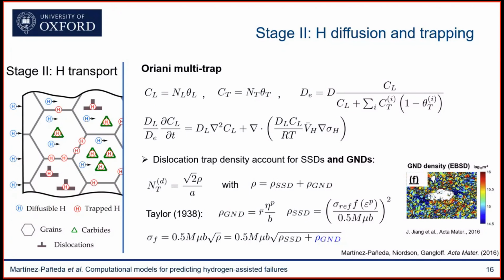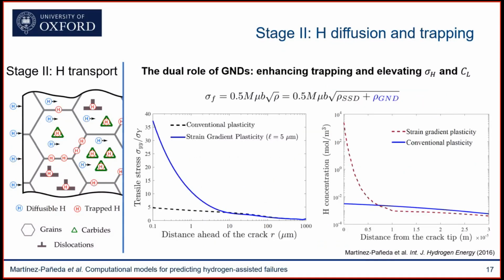And this is important not only due to the role that these dislocations play on trapping, but also due to the role that GNDs play in elevating crack tip stresses. We know that these GNDs act as obstacles to the transport of dislocations, to the movement of dislocations, and therefore bring some local hardening in areas where you have high gradients of plastic deformation. And you can see this here.